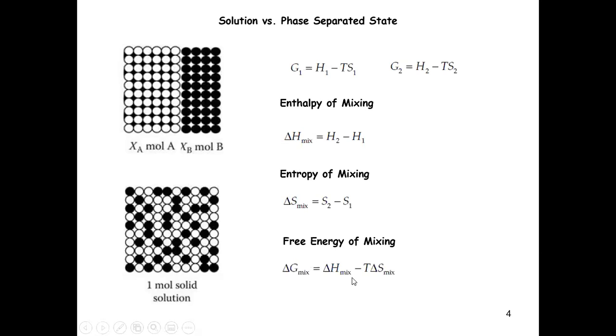Now, the only term that can possibly compete with this guy is going to be the enthalpy of mixing. But if your enthalpy of mixing also favors the mixing state, which means that by mixing you decrease the interaction energy, then these two contributions will both favor mixing. So there's no way for you to go back to the demixing state. This is independent of temperature, right? So for those systems, the behavior will be fairly boring. You can always see mixing is the favored state. Did that make sense to everyone?